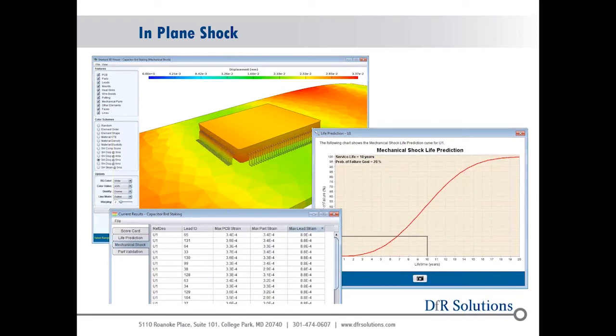So, that makes it difficult to model, but we use a combination of tied contact surfaces, so I can tie dissimilar meshes together. And you can see here as I'm getting the strains in the part, the strains in the leads, and then we actually get, because this part is moving back and forth, low cycle fatigue prediction for those leads as a function of time. In this particular case, I think it was 100 drops spaced over 10 years. So this is saying, probably going to get about 10% failure after about 70 drops.